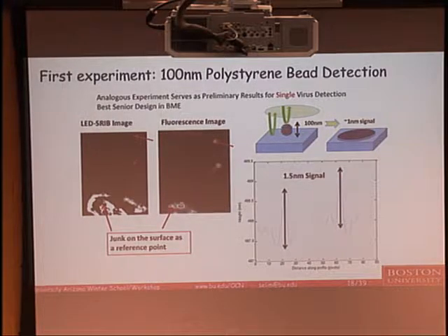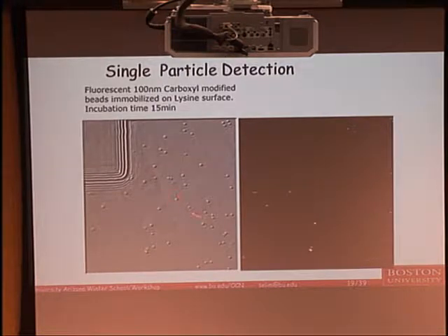And people didn't believe me. I said, okay, let's assign this to a couple of undergraduate students. And they did it, and they won the Best Senior Design Award with this data, which is this picture, right? They had 2 particles. They were fluorescent labeled. They were identifying them in the fluorescence image, and they looked at the surface profile. And this was a signal about 1 nanometer in height. They said, aha, we can see them.